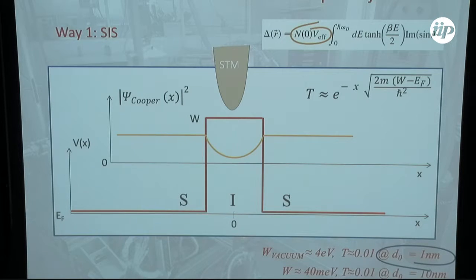So if you use standard Josephson junctions, an STM experiment is not possible. There are two options, and we explored one of them. The first one is to decrease the work function of the insulator, for instance, using a low band gap semiconductor. If, instead of 4 electron volts as for vacuum, you put 40 milli-electron volts, this extent for the same transparency could be 10 nanometers. And with 10 nanometers, quite a wide junction, you can indeed go and probe.